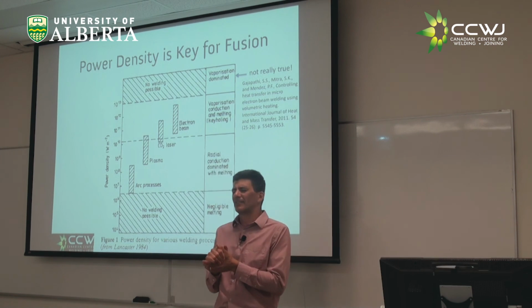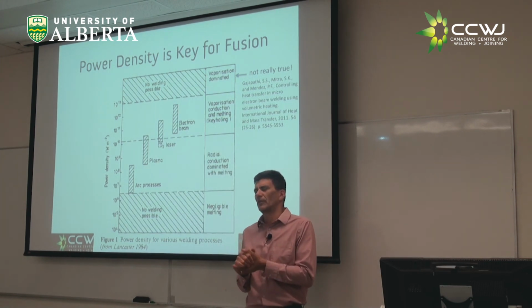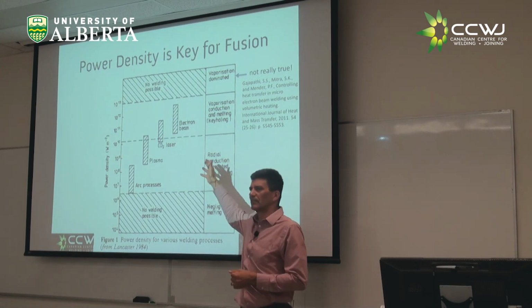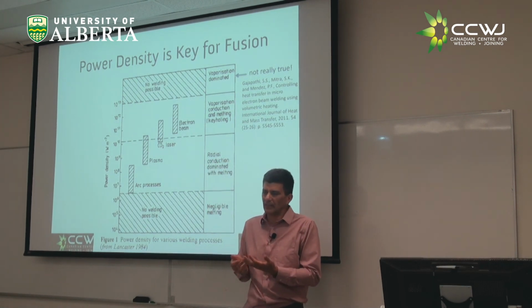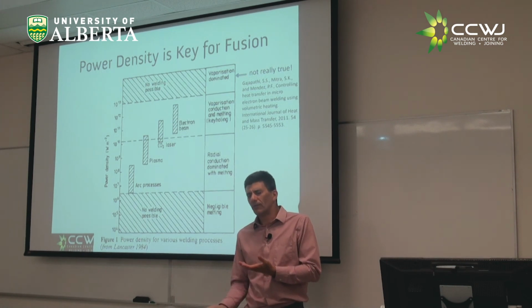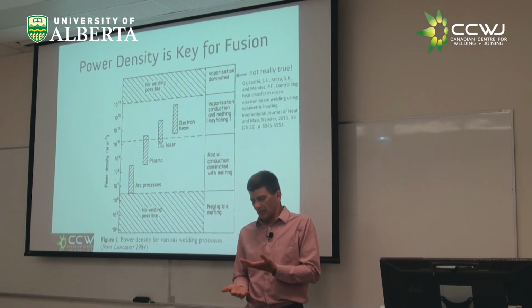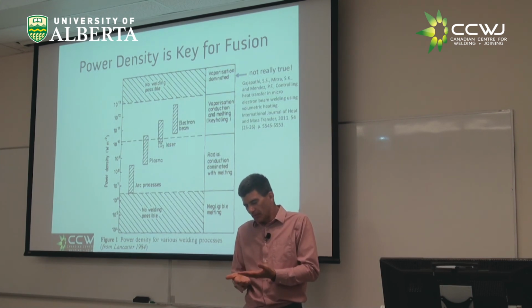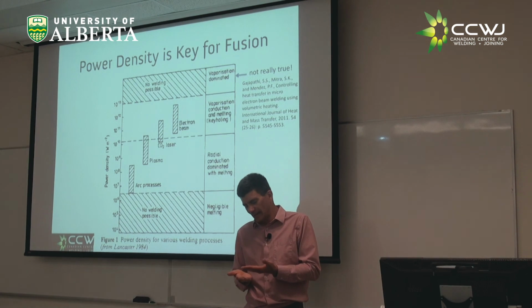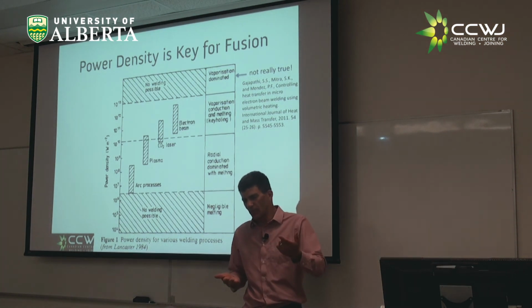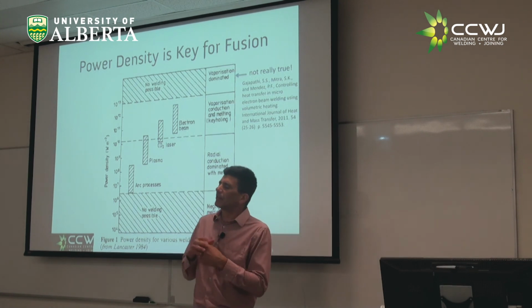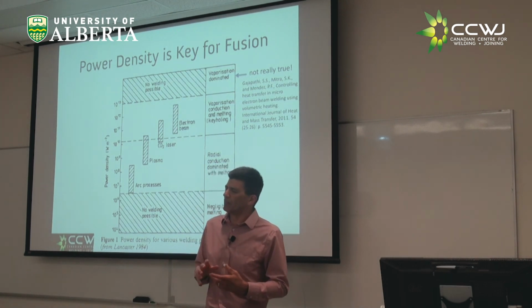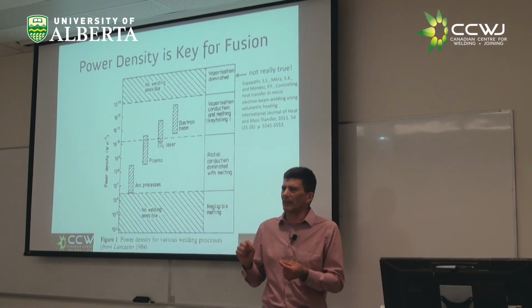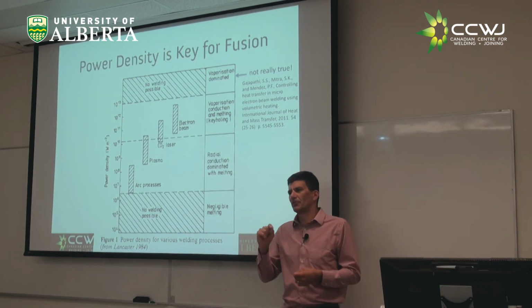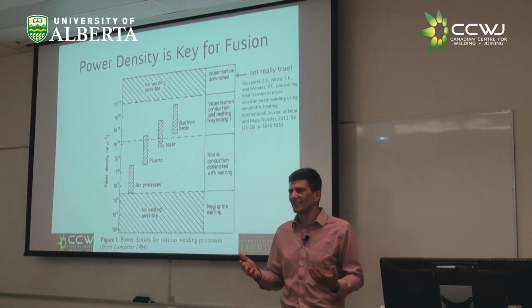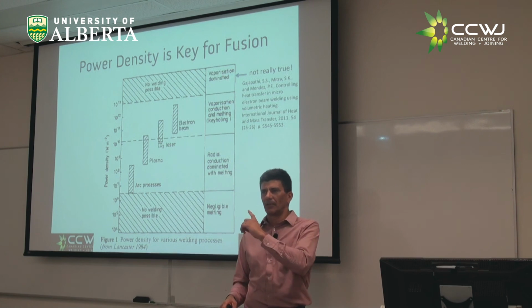But the funny thing is that it's not the whole truth, because this is all done on the assumption that you put heat on the surface and the heat needs to travel under the surface. For the heat to travel under the surface, you need a gradient. So if you have too high energy density, too intense a heat source, the gradient is going to be so big that you ablate. Now, things like electron beam welding are like that for the most part. But if you're talking about micro electron beam welding, you have a penetration of the electrons that gives you volumetric heating. And then you're not constrained by these gradients. And then all of a sudden, you can do what is considered impossible.